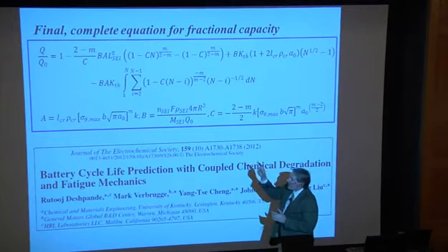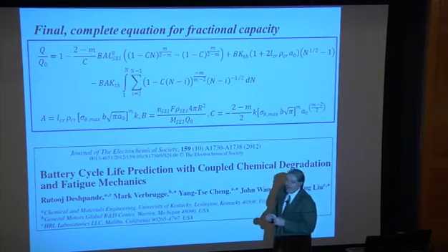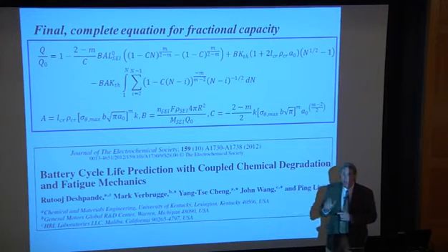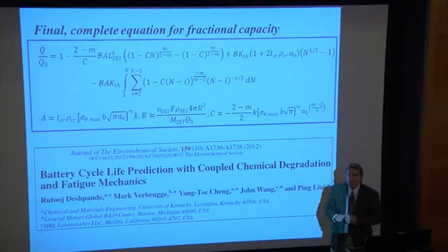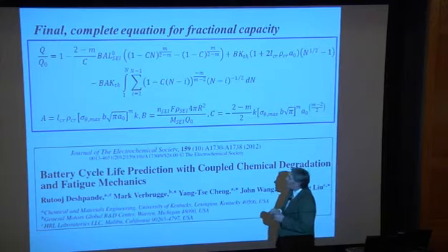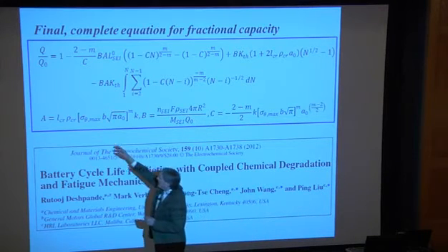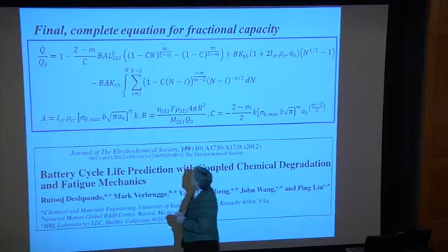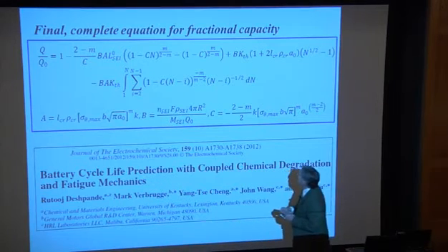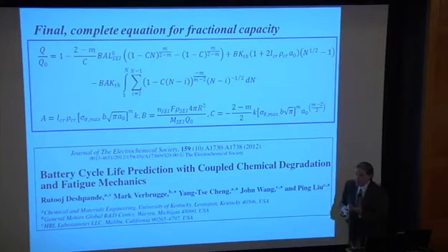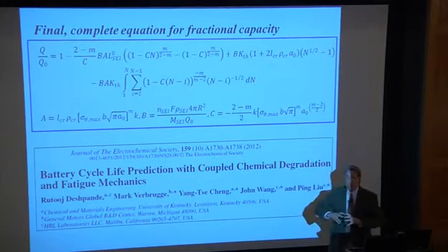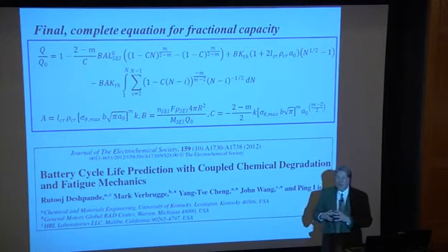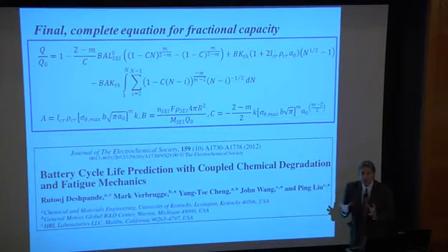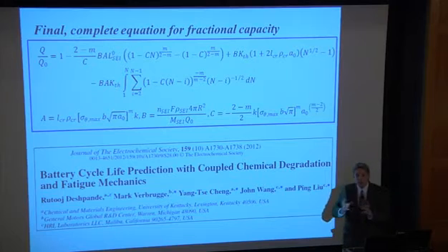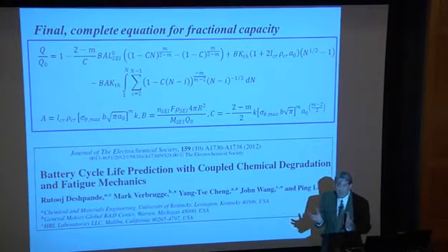I won't walk through this, but the left-hand side is the fractional capacity. So initially that quantity is 1, and it's going to degrade from 1 to, for example, in the volts case, about 0.75. And factors that show up are things like the maximum tensile stress at the surface, and I don't have all the parameters showing up here, but you'll see things like modulus of material, Poisson's ratio, those things you expect to see from solid mechanics as you expand and contract a particle due to concentration gradients in the particle, just like thermal gradients give rise to thermal stresses in thermal elasticity calculations.